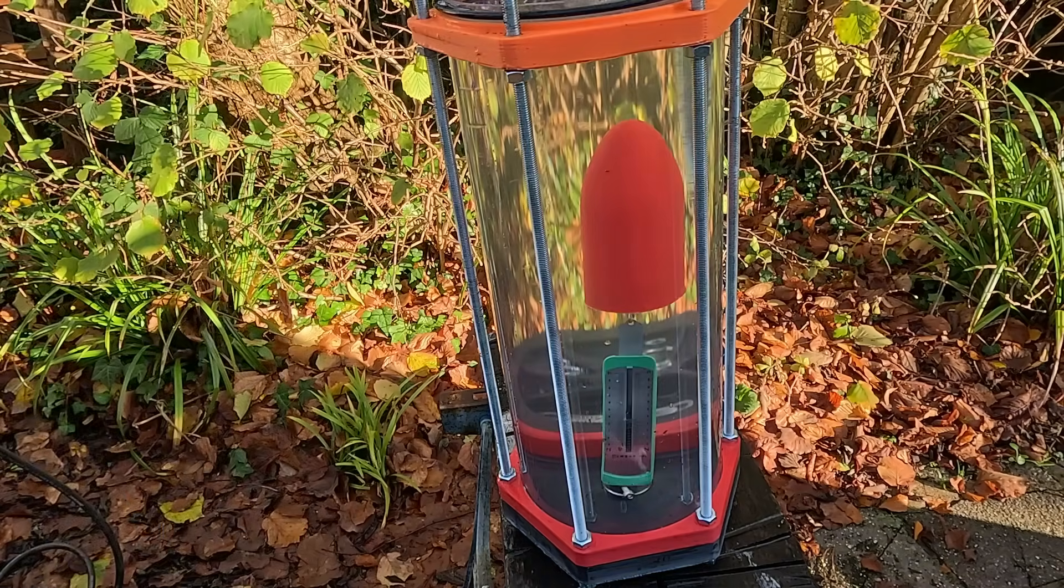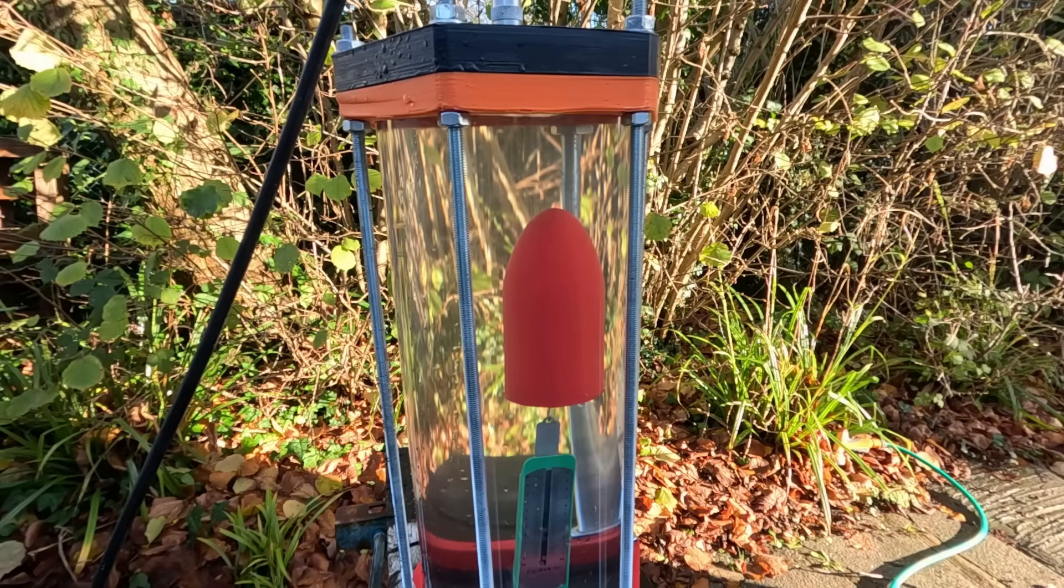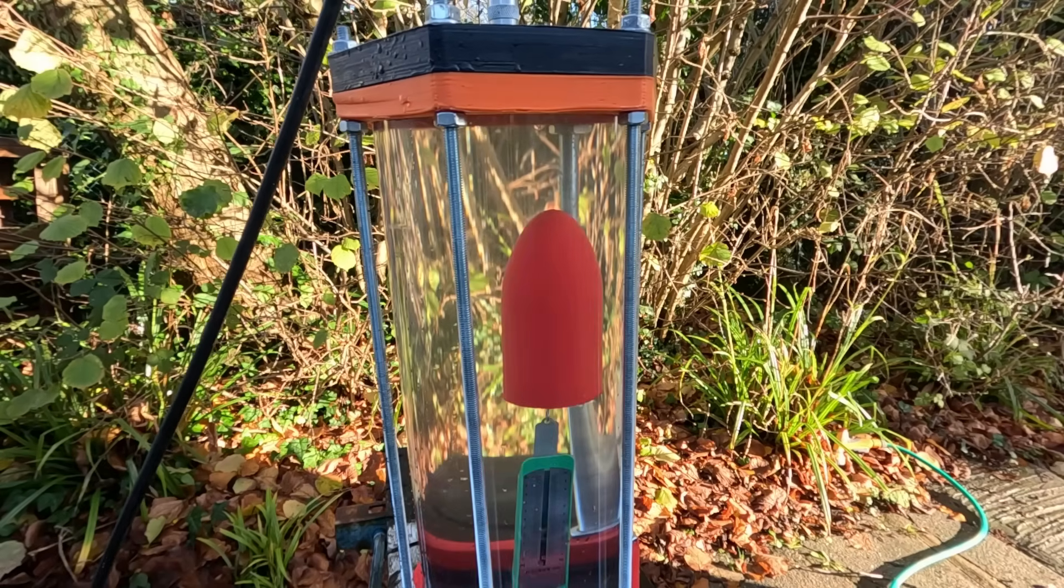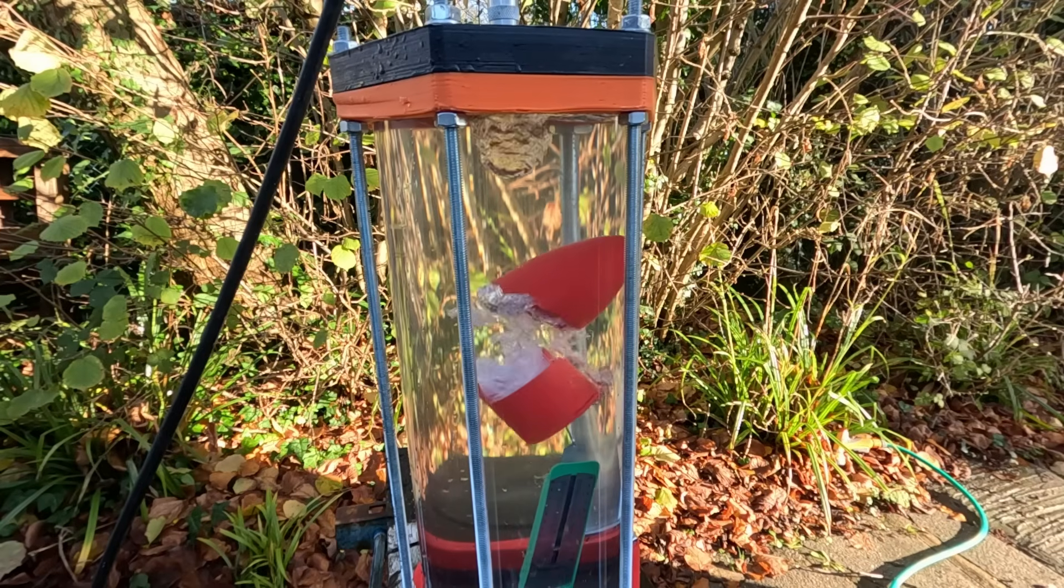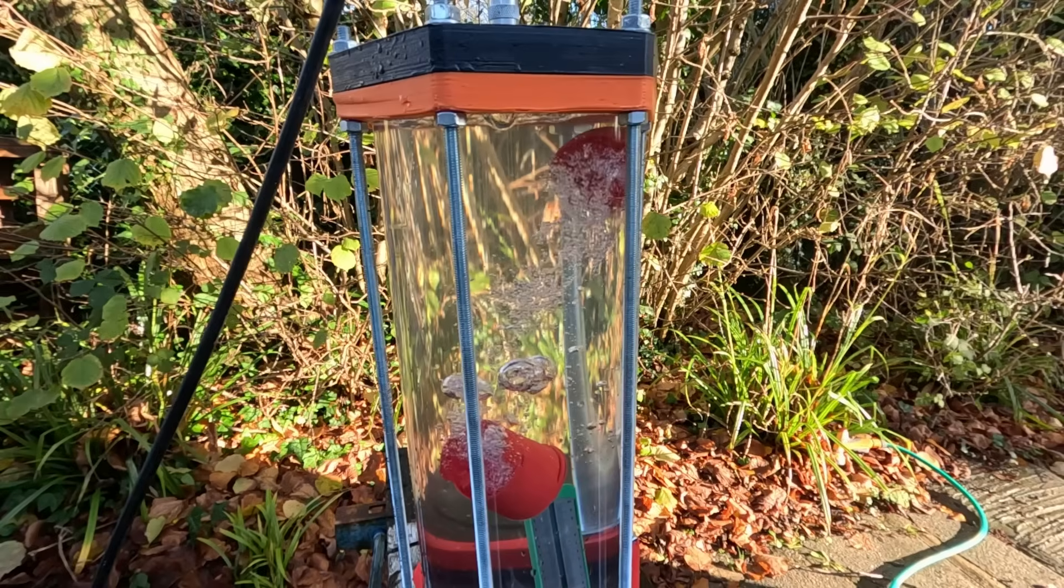I wanted to end with an illustration of just how much force 40 meters of water pressure is exerting on the hull by testing a slimmed down 1.2 millimeter hull in the test rig at 4 bar. Here we go. It didn't stand a chance. Now again in 10 times slow motion. You can see quite clearly how the hull buckles and fails in multiple regions in less than a tenth of a second.